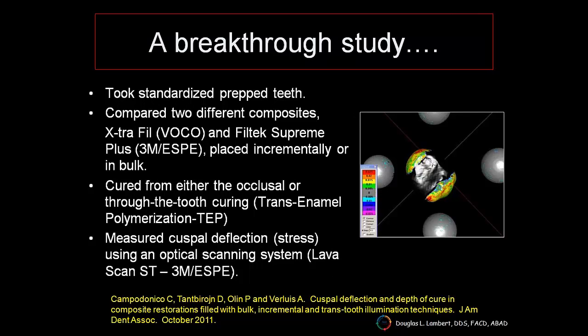In this study, they took standardized prep teeth and compared two different composites, ExtraFill and Filtek Supreme. ExtraFill is designed to be a bulk fill material, and Filtek Supreme is a classic anterior-posterior universal composite. They placed some samples incrementally and some in bulk. Then they cured some from the occlusal only, or used through-the-tooth curing, trans-enamel polymerization. They measured the cuspal deflection, a measurement of stress, using an optical scanning system. And it's interesting, the results that they got.